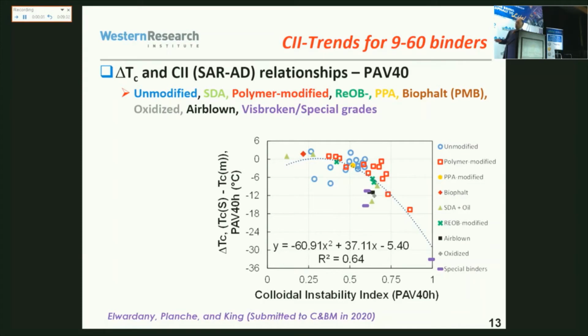So when we take the delta TC that we measured under PAV40h and we plot it as a function of the colloidal instability index, we have this type of relationship. It's not a strong correlation, right? 0.64. But I think it's important to spend some time and think about it. What do we have here? So there is the color code for the polymer modified. So you see all the polymers on one part of the curve, and then there are all the others.